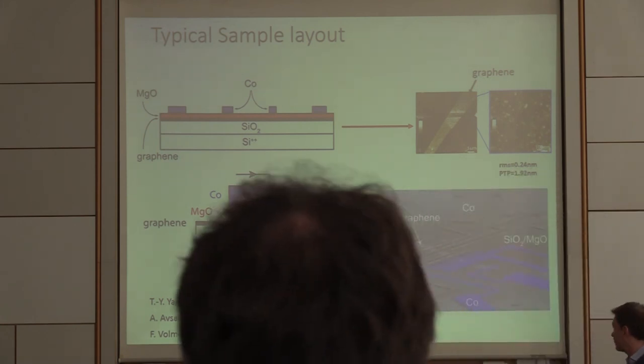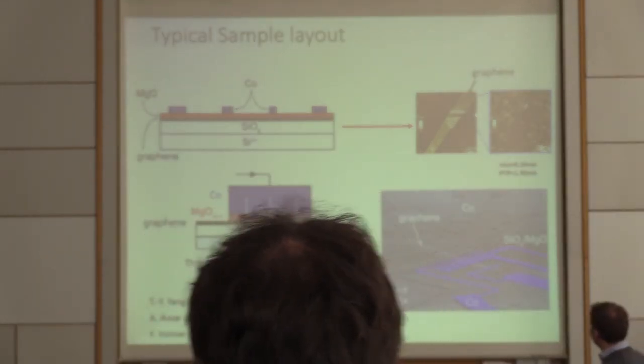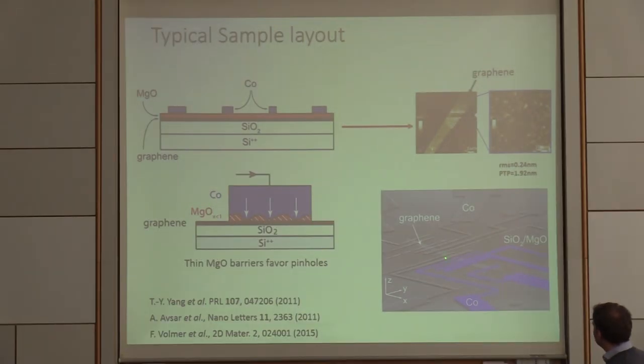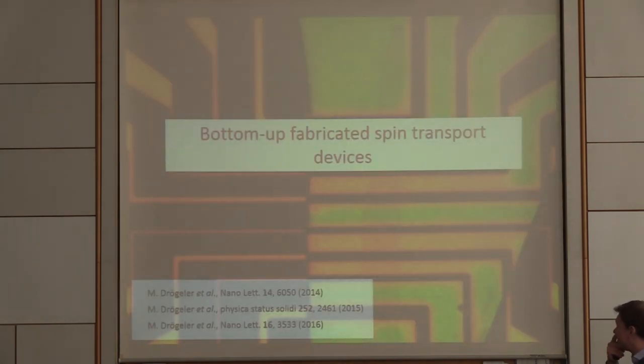The interface forming on the graphene, graphene is not a good seed layer for growing MgO, and in particular, it really leads to a lot of pinholes in this system. One has to find ways of increasing the quality of the interface between the tunneling contact. So the ferromagnet, then we need a tunneling barrier and then we need the graphene. And by placing everything on silicon oxide and putting the contacts on top, I think that is not a very clever idea.